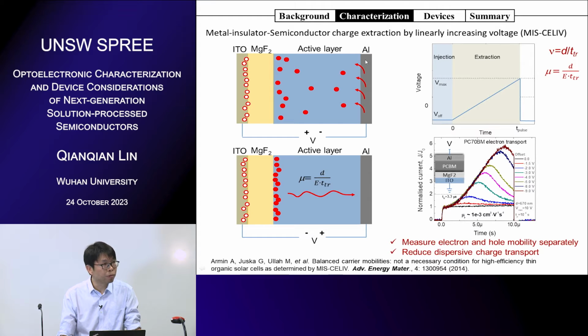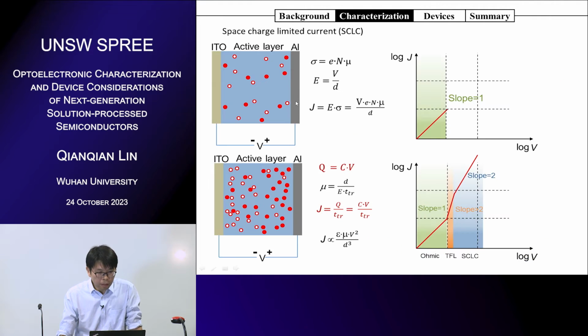If we use aluminum, we normally inject electrons, and if we use gold with high work function, we can inject holes. So from this method, we can distinguish hole and electron mobilities. But we still have kind of dispersive transients because all carriers can get scattered. These three methods are all transient measurements, so they are time resolved. We do need a faster oscilloscope.